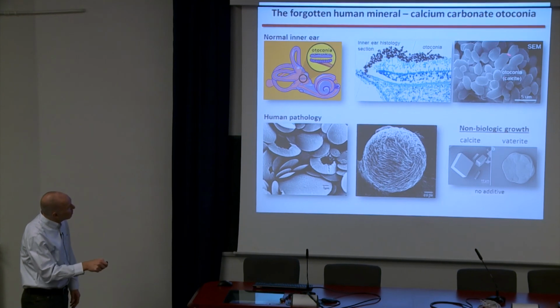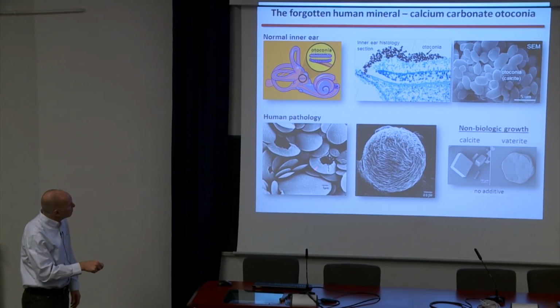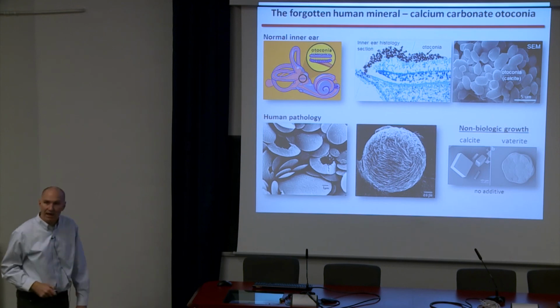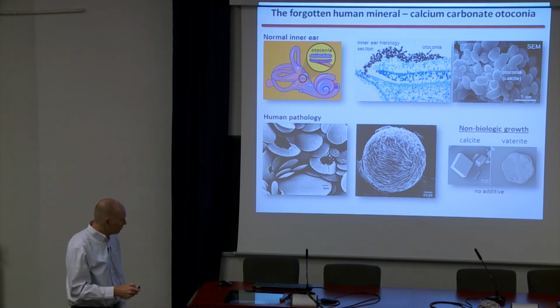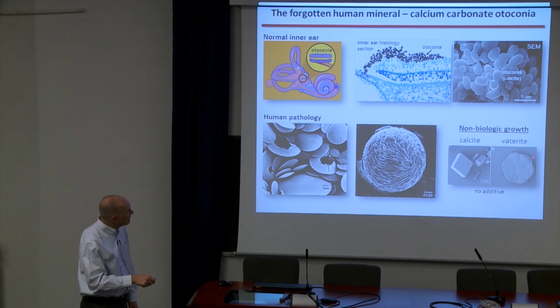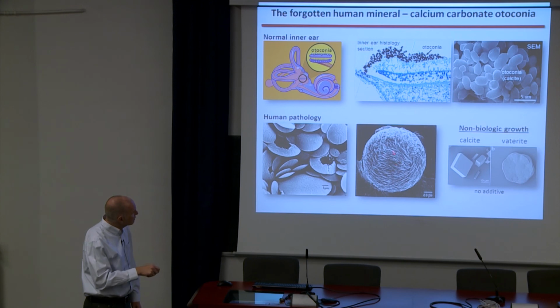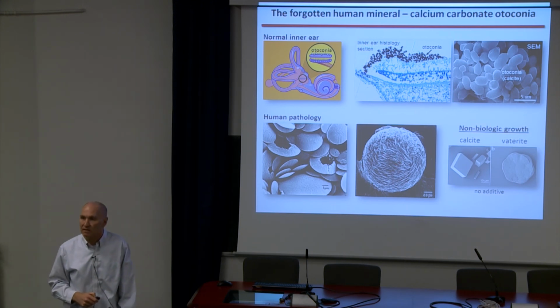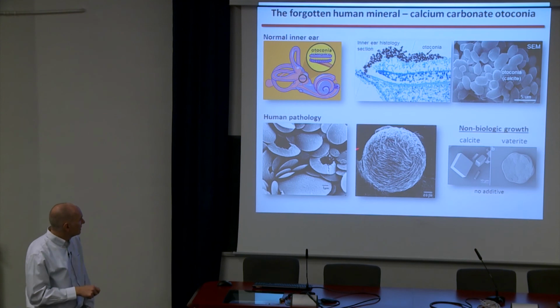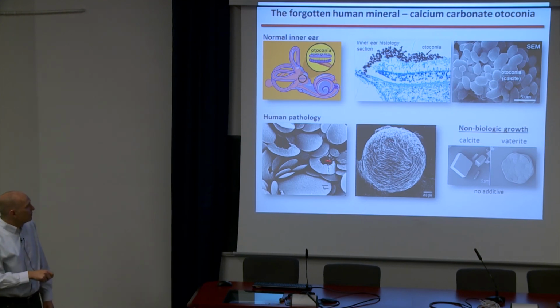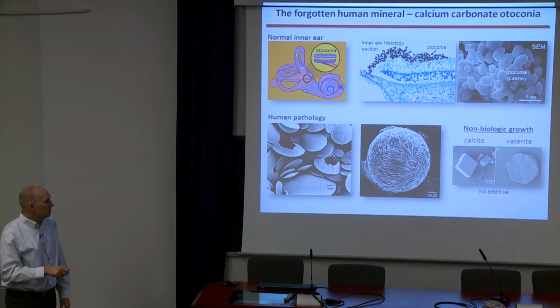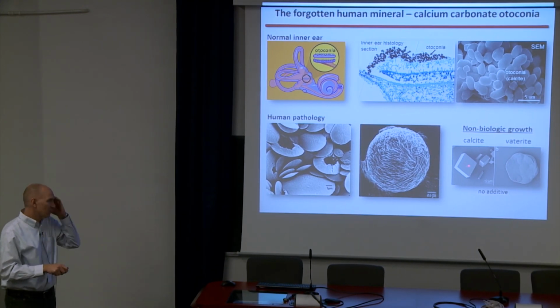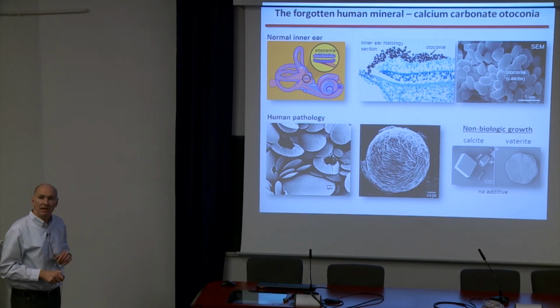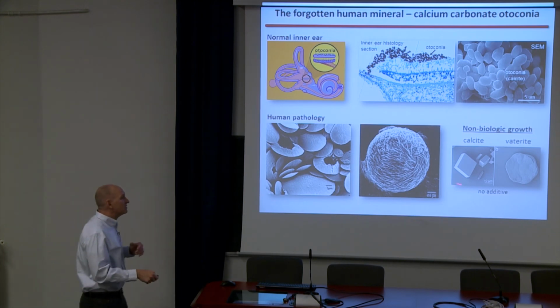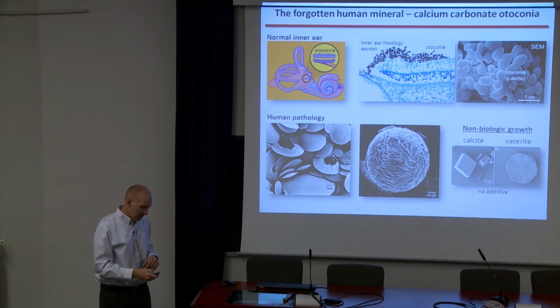Interestingly, human otoconia normally look like this, but there are case reports that we dug up of otoconia having this shape. And those in the calcium carbonate field know that this maybe looks a bit like vaterite calcium carbonate. And then there are these discoid structures with platelets of mineral. It's also vaterite. This article characterized these minerals as vaterite. But this is not what it's supposed to be. It's supposed to be like this. And you know that calcite polymorphs are more stable, but you always get a bit of vaterite. And organics can stabilize and keep your vaterite.